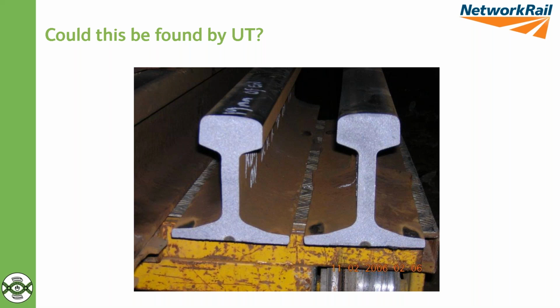Can we distinguish that from general noise from the rail foot because of a degree of corrosion, general corrosion, some surface irregularities? They all produce ultrasonic signals, but it's something we spent a couple of years looking at, unfortunately not with any positive confirmation of this type of defect, and perhaps understanding more about how quickly it grows. Is it a sort of single event? Is it a few events? But certainly you can see from the size, it's quite a challenge to find something that small in the foot of the rail. It's a long way from your ultrasonics at the top of the rail, and you get a lot of noise back from the general surface irregularities.